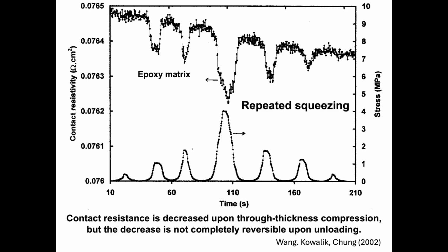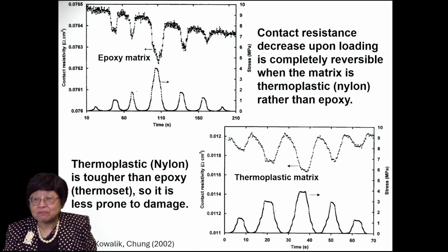And so this is the contact resistivity versus time during repeated squeezing (stress variation) as shown in the bottom curve. And the upper curve is the contact resistivity. Every time one squeezes, the contact resistivity goes down, and that is because one is increasing the proximity between the fibers of the adjacent laminae. However, note that upon unloading, the resistivity doesn't return all the way back. That means there is some degree of irreversible microstructural change. Could be very, very minor damage.